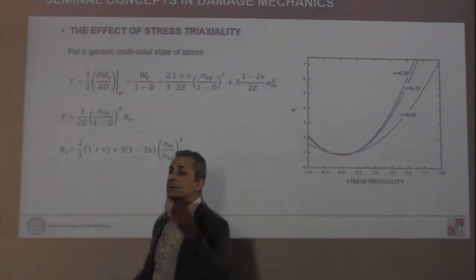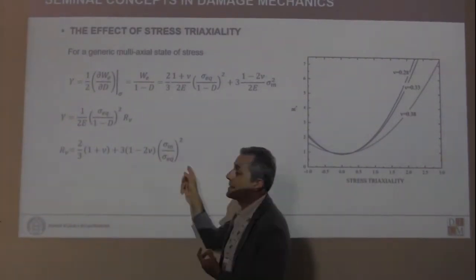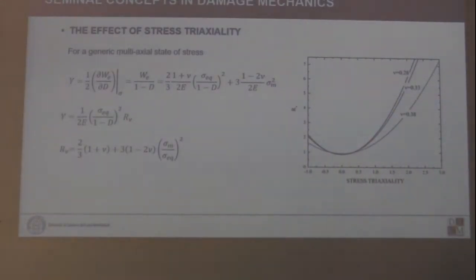Another beautiful result is the fact that the effect of stress triaxiality on ductility can be theoretically derived without the need of additional hypotheses. Just partitioning the strain energy into the volumetric and deviatoric part, we come up to this relationship in which Y, the associated variable to damage, is a function of R_v, where R_v is a function of stress triaxiality. This gives you directly, without the need of additional hypothesis, the fact that the more triaxial the state of stress, the lower the ductility the material would exhibit. This is a fundamental concept that was initially demonstrated experimentally in the 60s by McClintock and Rice and Tracey, but in this framework, it just came up as a result of the formulation. We don't need any additional hypothesis.